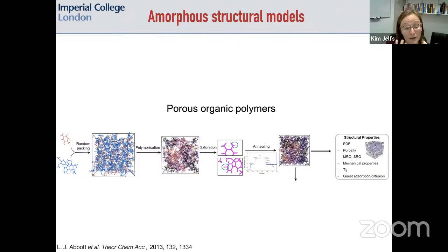But you do the same procedure. You take the monomers of the PIM you're making and load them into a very large box at a low density. Then you do the polymerization procedure, where you form hundreds of bonds and do lots of annealing to allow the structure to relax. When you're finished with the polymerization, you do sensible chemical saturation of any of the unreacted end groups. And then you do a very long annealing procedure at different temperatures and pressures and so on to try to get realistic structures. That typically makes the structure much more dense than you get at the end of the polymerization. And then obviously you can do lots of analysis of the structural properties of the system.